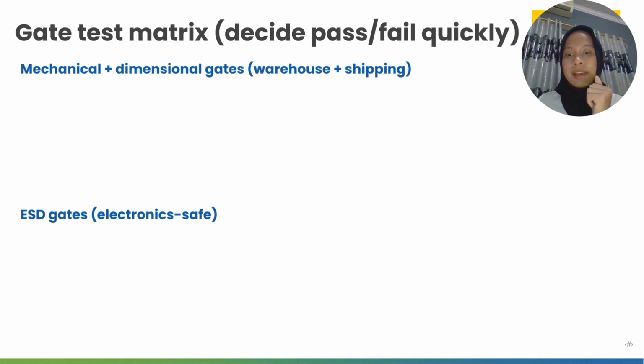And the next one is ESD gates, or electronic-safe gates, where the test is surface resistivity and the passing criteria is moved from 10^5 to 10^11 dissipative range, and the note is to confirm the target spec with the customer. And for static decay time, the passing criteria is charge decays rapidly, and the attraction handling is a visual plus particle adhesion test.